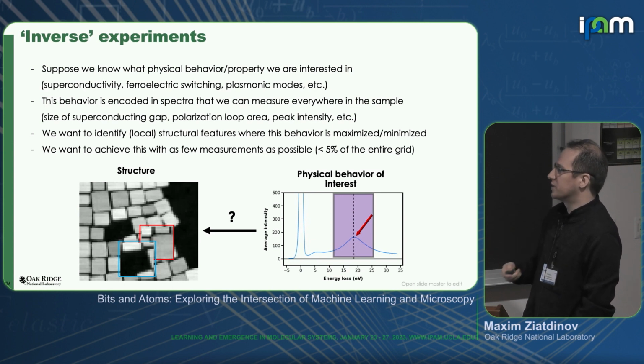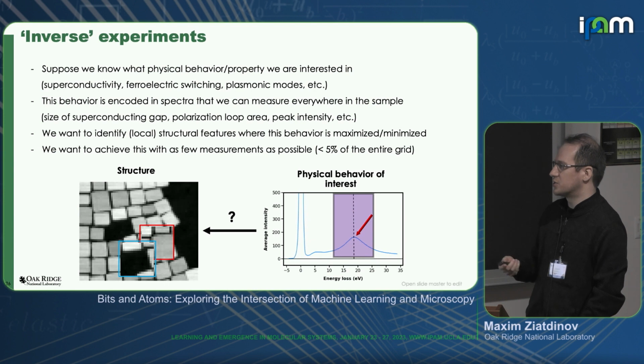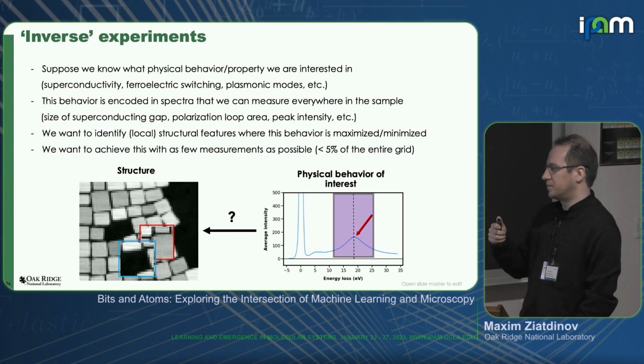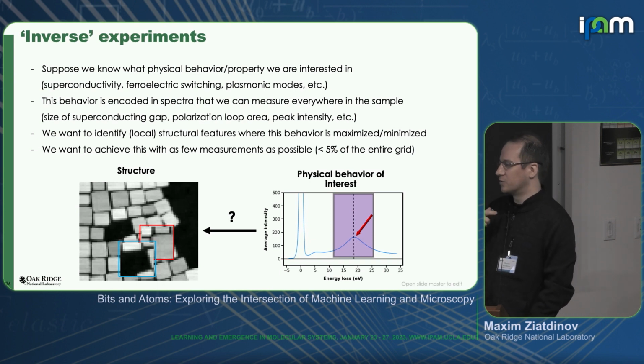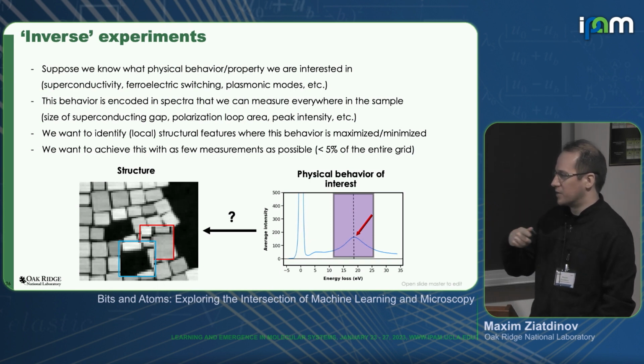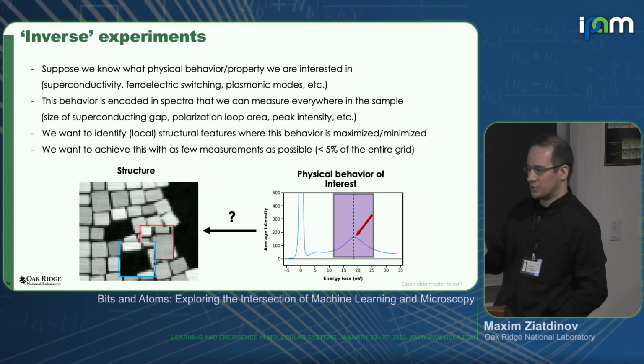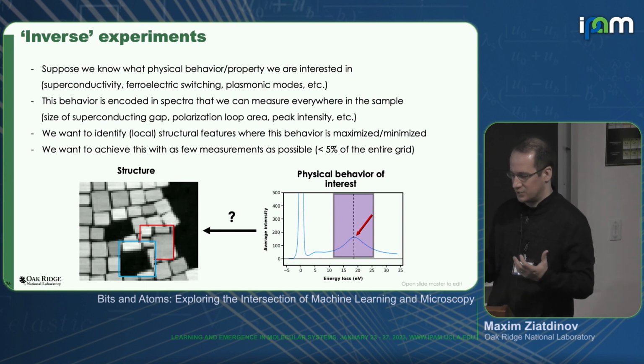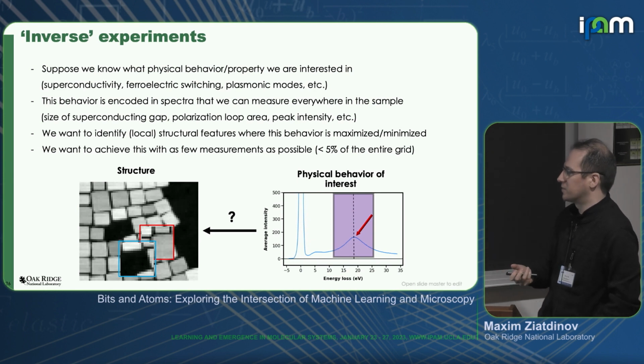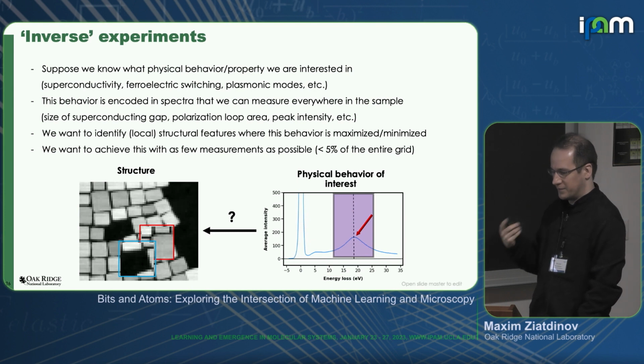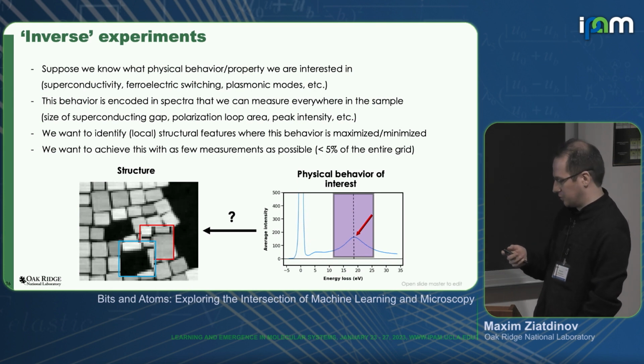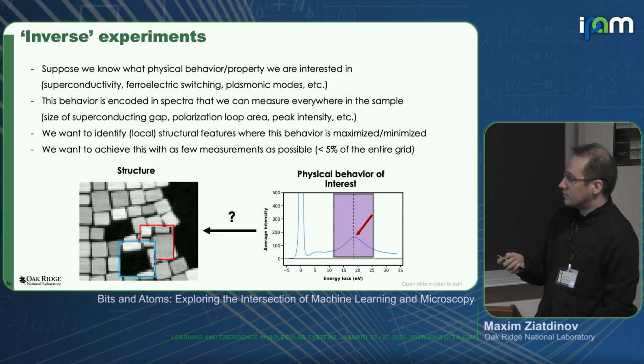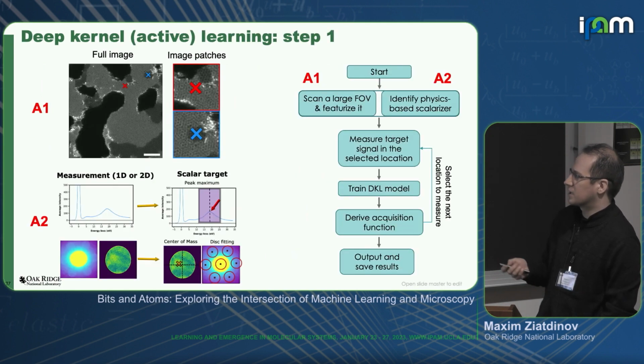And we want to do it with as few measurements as possible, ideally by measuring less than 5% of the entire grid. And the reason for that, well, first of all, there are beam-sensitive materials, like the material can decompose if you measure it for too long. So the material will get destroyed before you can even complete your measurement. There are some other time, financial, and other constraints. So you want to do it really fast. Okay, and that's how we do it now.